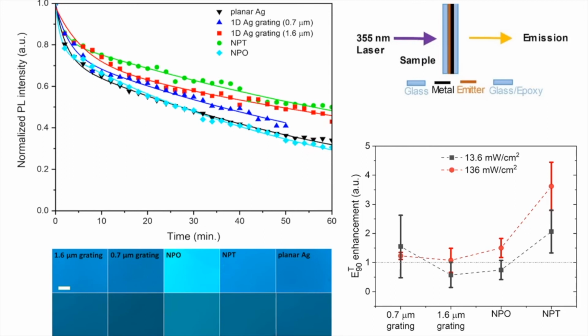We did many of these stability measurements and took statistical averages and standard deviations of the data that's shown here. And you can see that this was also done at two different excitation powers. You can see that the nanoparticle metasurface consistently improves the stability of the emission from the phosphor compared to the other surfaces. And in general, you'll see that at higher powers, the stability enhancement is better than at lower powers. And that's consistent with the idea that we're minimizing triplet-triplet annihilation, because triplet-triplet annihilation should happen more at higher powers. So this idea that we're shortening the lifetime should have a bigger impact at higher powers, and that seems to be showing up in our data.